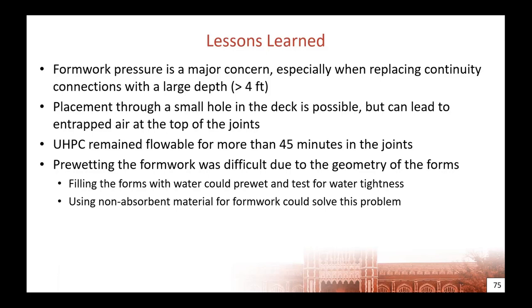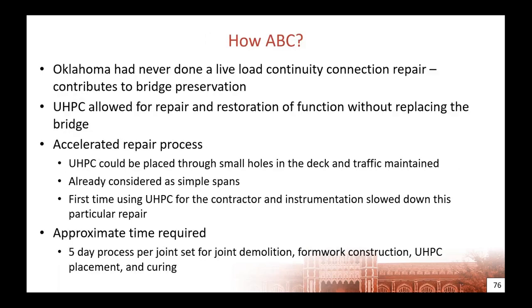And one thing that you can do to kill two birds with one stone is to conduct your own water tightness test. Just fill the entire joint up with water and see if water leaks out. And if it doesn't, just let it sit there for a bit and let the formwork and the concrete suck up some of the water, and then pump all of that out. And you can place the UHPC knowing that it's a watertight joint. That way you have water absorbed in your formwork, and also in the existing concrete, so you're less likely to have the issue of UHPC sticking to the formwork.